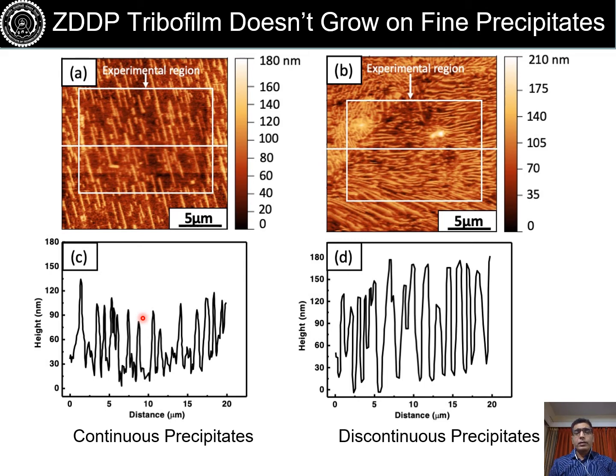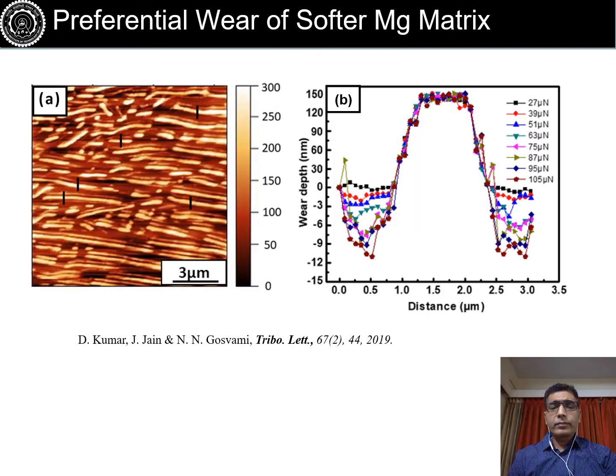And we have seen in the previous first experiment, where I showed wear of tribofilm at elevated stresses, that is probably what is happening here: these stress concentrations and stress variations are not allowing tribofilm to develop on the surface, and this corrugated surface prevents smooth or stable sliding of the probe, which is required for shear of these molecules so that they can react at the interface.